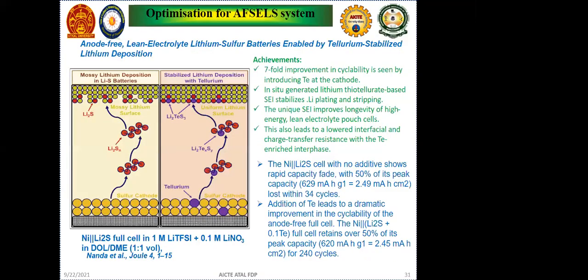So one of the strategies, as I mentioned, is that when we dope other transition metals into the lithium sulfide system, the activation energy of the Li2S reduces. As you'll see, this group from Professor Manthiram used tellurium in this Li2S system, so that a lithium anode free battery will be developed, and the capacity is very nice, and the life cycle is also very high. The sulfur system is also working nicely, because this tellurium is captured, and it doesn't allow the Li2S to degrade faster.